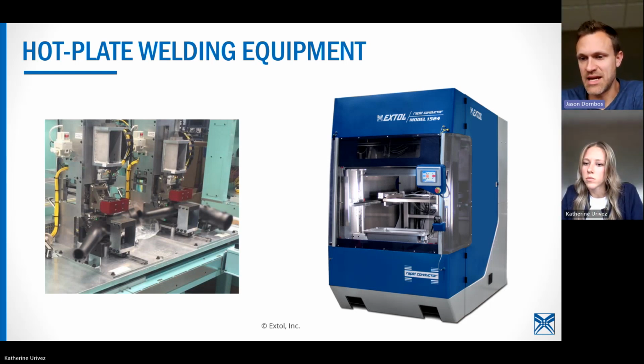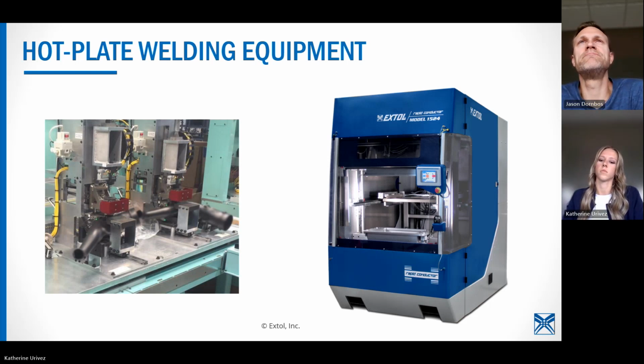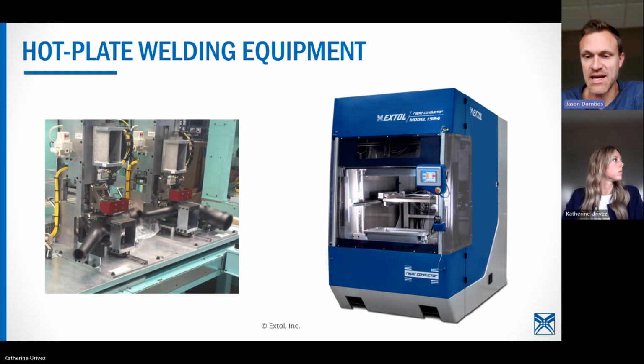You mentioned a temp up to 800. This is far away from typical melting temperature plastics. Yes, it heats it quickly. What is with the flash? This flash will be thermal degradation. The flash, when we're using those higher temperatures, we're not melting for very long. And we'll see that in a video here in just a minute. There might be small amounts of degradation, but it's very uncommon for us to see any kind of material that's like falling off of a weld. Like that would be very rare.